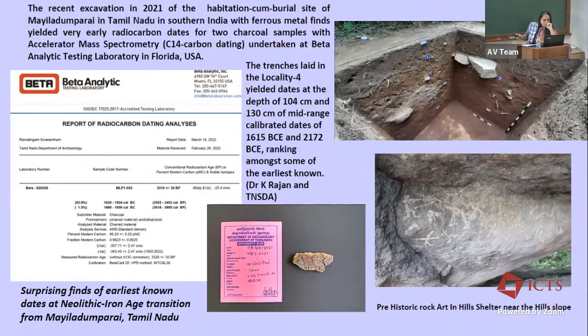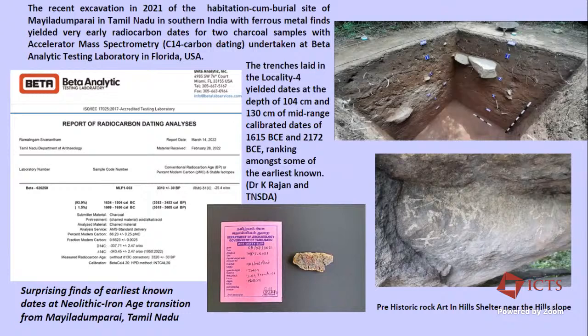But what I want to talk about here, just two slides before I finish, is I come back to this interesting point of the recent finds from Mayiladamparai. Now, it's been generally thought that the smelting of iron and so on came about with the Hittites and then spread very rapidly from those parts, Anatolia and so on, into other parts of the world, including at some point diffusing into the Indian subcontinent. But in these excavations in Mayiladamparai, we found some very early carbon dates, which were actually done with Beta Analytic in Florida. And these yielded mid-range calibrated dates of going back to 2172 BC. And these are actually the earliest known dates in iron now.